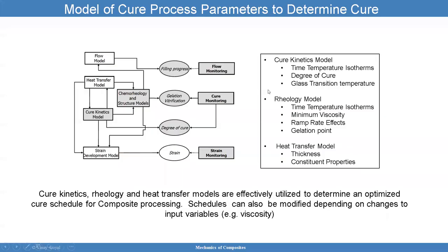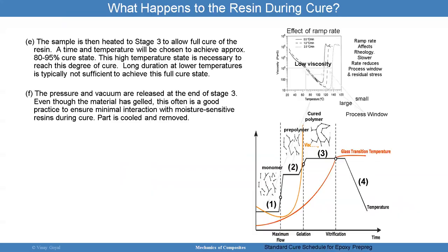I want to point out that there are a lot of models that have been developed to model the cure process. But it's very complex and it requires a heat transfer model, flow models, cure kinetic models, and structural analysis models. And the cure kinetic models require being able to model the time temperature isotherms, the degree of cure, glass transition temperature, and so forth. So these models have been effectively utilized to determine an optimized cure schedule for composite processing. People have used these analytical models to really optimize what this looks like for a particular application, pressure and temperature.